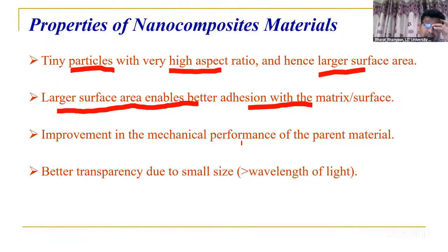Then improvement in mechanical properties of the parent material. That means where you are adding this material and dispersing it, the mechanical property will improve. Example: we took PVC pipe, polyvinyl chloride. If you prepare it only with polyvinyl chloride, that pipe is flexible. But if you add calcium carbonate nanoparticles, its strength will increase. So that's why you can use PVC pipe with the addition of such materials. So the mechanical strength will improve. Better transparency.